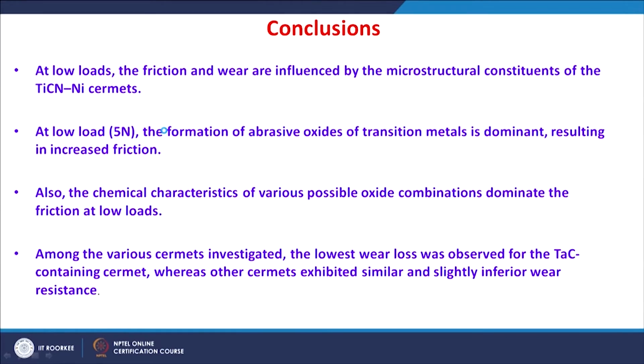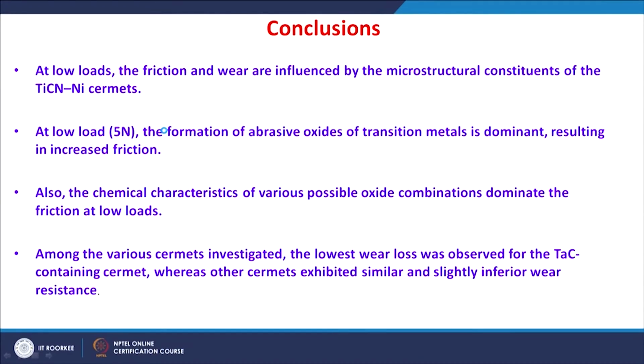So, the overall conclusions from the present study: at lower loads the friction and wear are influenced by the microstructural constituents of these titanium carbonitride nickel based cermets. At lower load, that is at 5 Newton, the formation of abrasive oxides of these transition metals is dominant, resulting in higher friction. Also, the chemical characteristics of various possible oxide combinations dominate the friction at lower loads. Among the cermets investigated here, the lowest wear loss was observed for the cermet containing tantalum carbide, whereas other cermets exhibited similar and slightly inferior wear resistance.